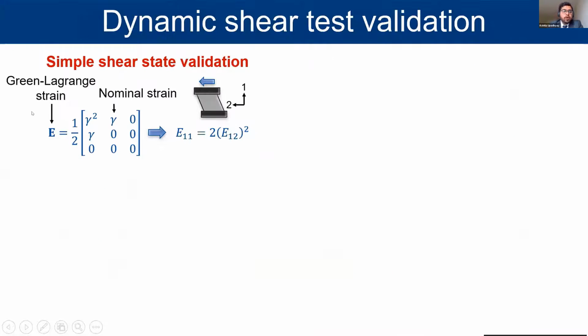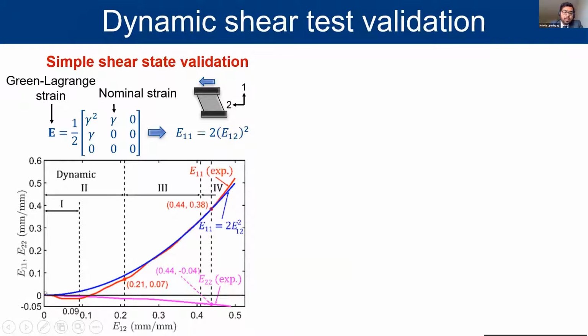However, before doing that, I want to validate if the deformation mode we are simulating is correct. In order to validate the simple shear state of deformation, I make use of the kinematic description of the simple shear state according to continuum mechanics, which says that the 1-1 component of the Green Lagrangian strain should be 2 times the square of the 1-2 component. To validate whether this is what is actually happening, I plot this blue line, which is the theoretical E11 versus E12 response, and compare it with the red line right here, which is the E11 versus E12 response obtained from DIC from the experiments. We can see that in the stage 3 of deformation, we get an excellent agreement between the theory and the experiment.